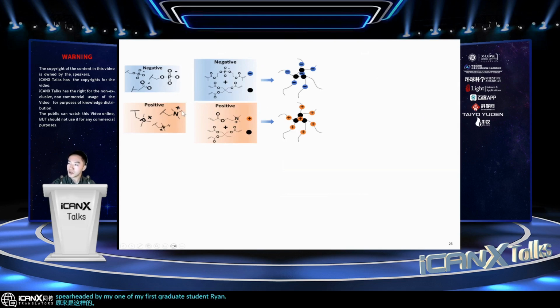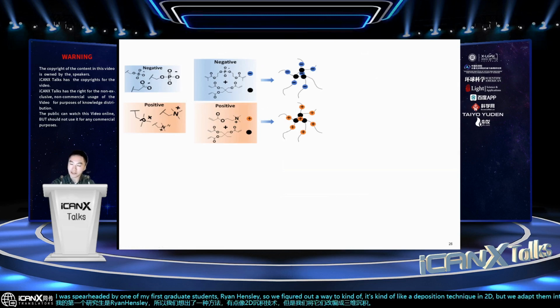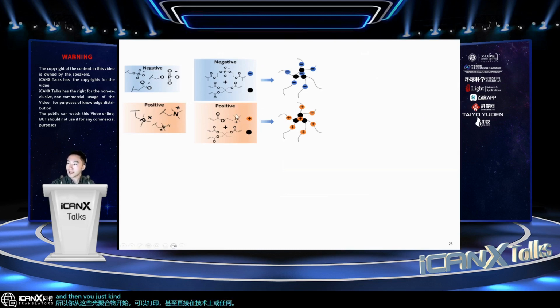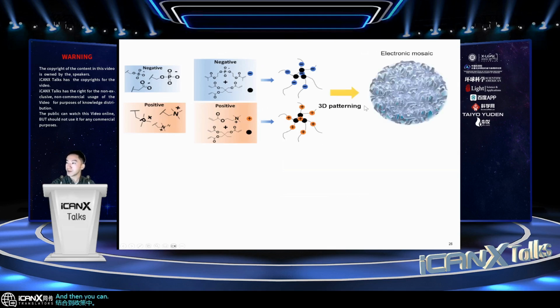So we figured out a way. It's kind of like a deposition technique in 2D, but we adapt it into three-dimensional deposition. So you start with these photopolymers that can be printable, or even direct ink technology, or any printable ink. And then you just combine them with electrostatic charges. So what do the electric charges do? They can basically be combined into the polymer, and then you can pattern using any regular 3D printing technology, multi-material 3D printing, into a three-dimensional scaffold.